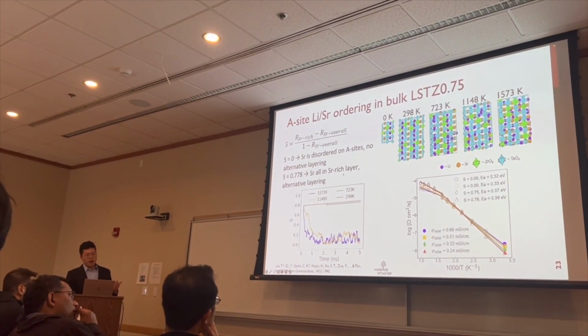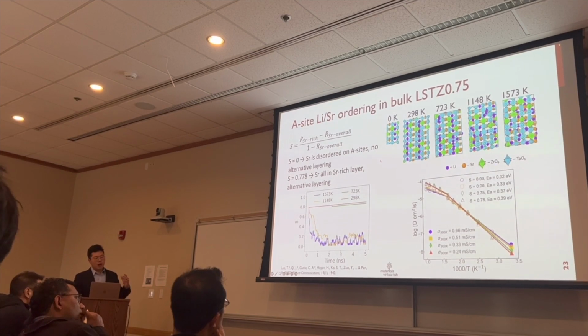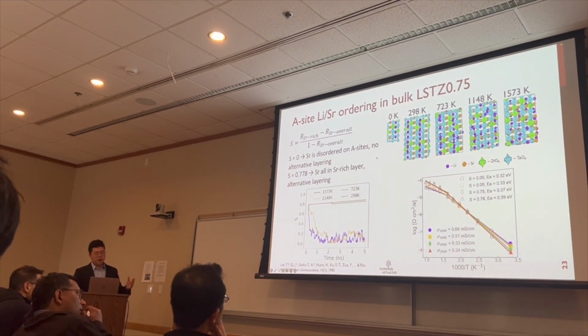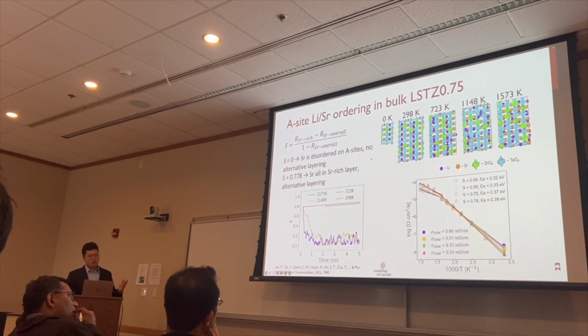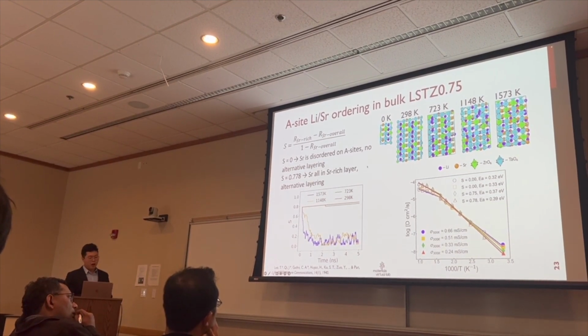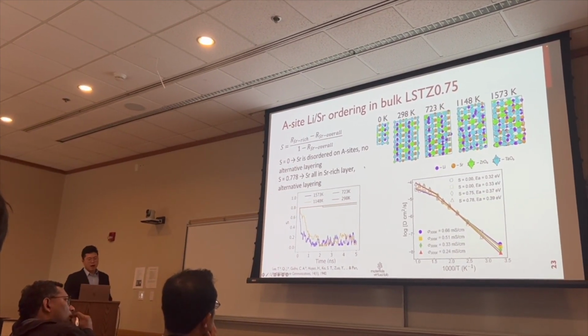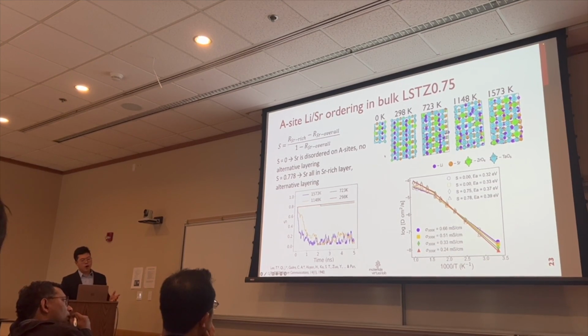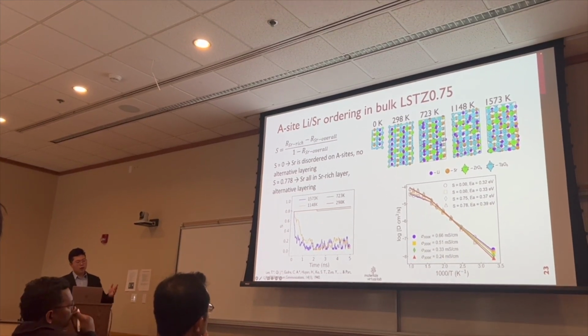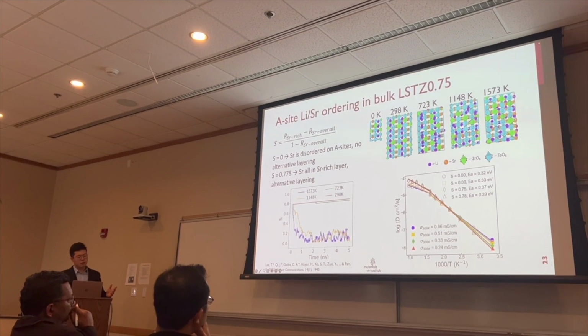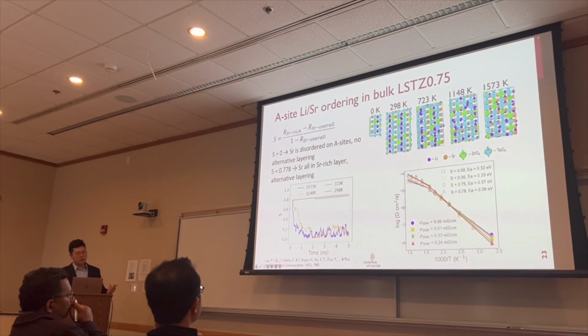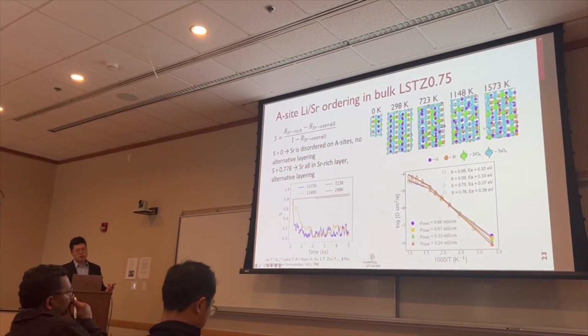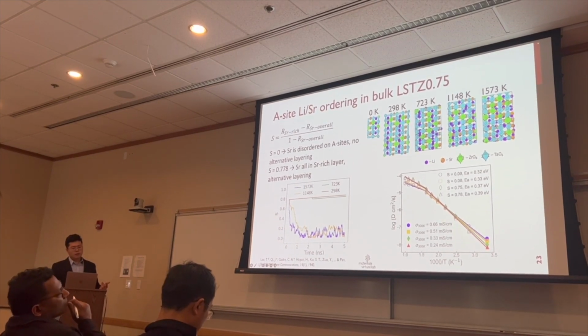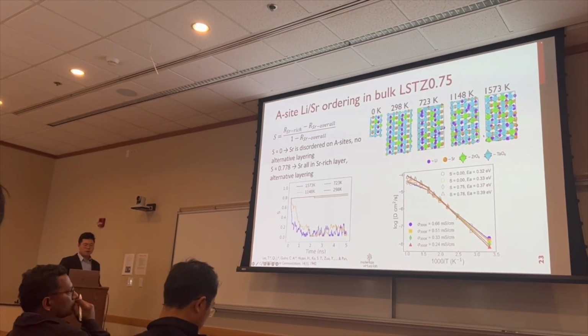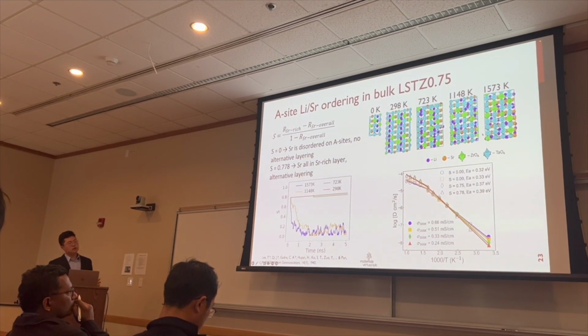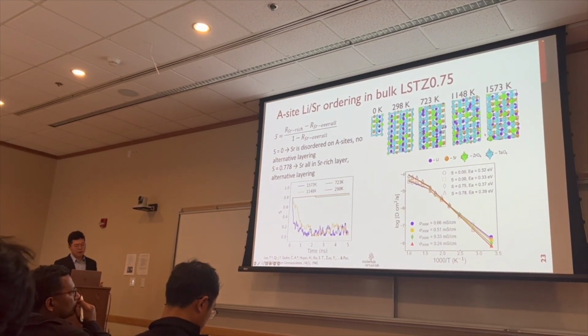Well, when we perform MCMD simulation to allow the atom swap between A site lithium and strontium, we can see that at elevated temperature above 723 Kelvin, the order parameter decreased to 0 during the simulation, which means that the A site is no longer ordered, and the lithium and strontium are fully disorderly distributed in the A site.